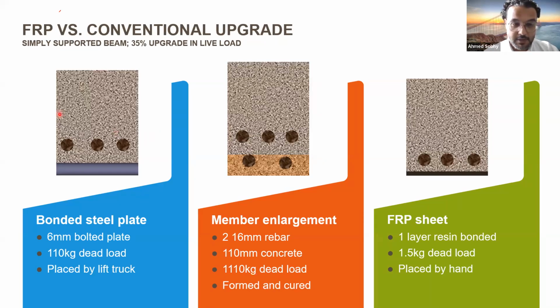For bonded steel plate, the design opted for a 6 millimeter bolted plate, which added about 110 kilograms of dead load, and it needed to be placed and lifted by trucks. For member enlargement, the design opted for adding a couple of rebars of 16 millimeters, and that needed a concrete cover of around 110 millimeters. This added about a ton of dead load, and it needed to be formed and cured. Using the fiber reinforced polymer sheet was literally one layer of resin bonded fiber reinforced polymer, 1.5 kilograms of dead load, and it was placed by hand. So obviously it was very appropriate to use fiber reinforced polymers in this instance rather than the two other options.